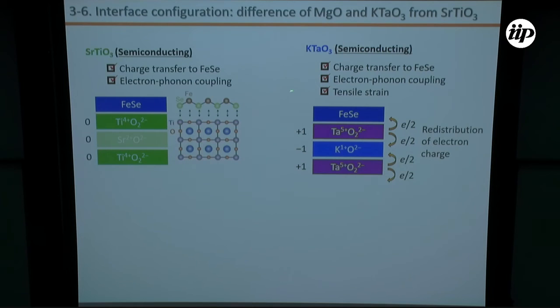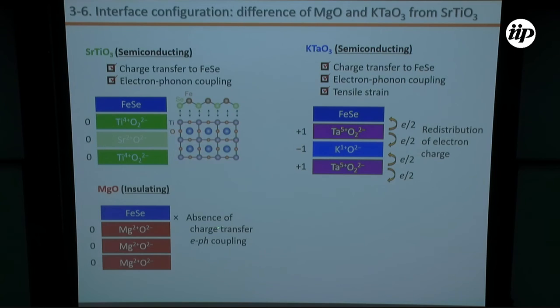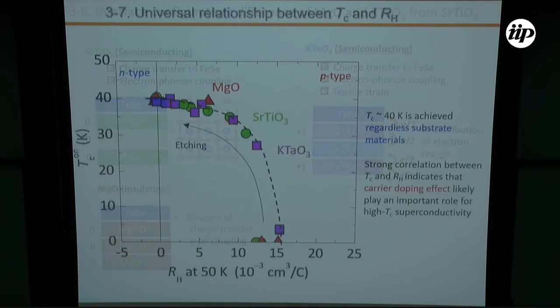And potassium tantalate is one of the polar materials, with plus charge tantalum oxide and minus charge potassium oxide. So at the top surface, the distribution of the charge results in charge transfer to the iron selenide, as shown in the previous speaker's talk on LAO-STO. However, in the case of MgO, the surface is very stable. There's no oxygen defect, and so there's no charge transfer. So in this case, the high TC superconductivity is induced only with the electric field from the top gate.